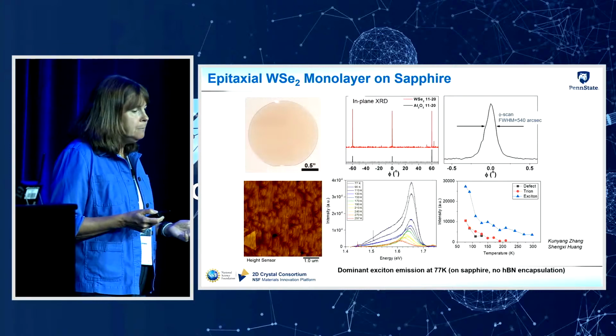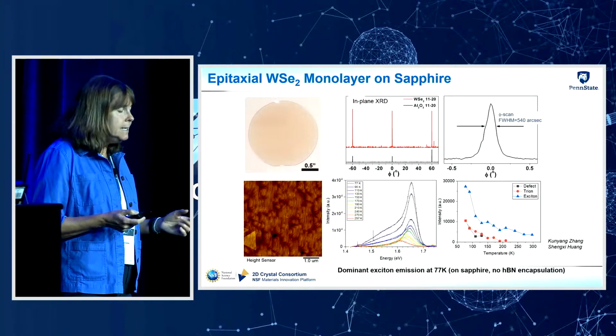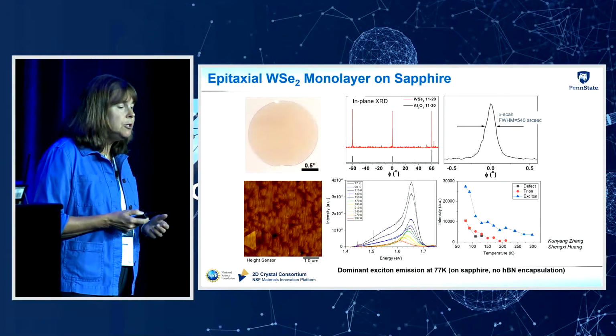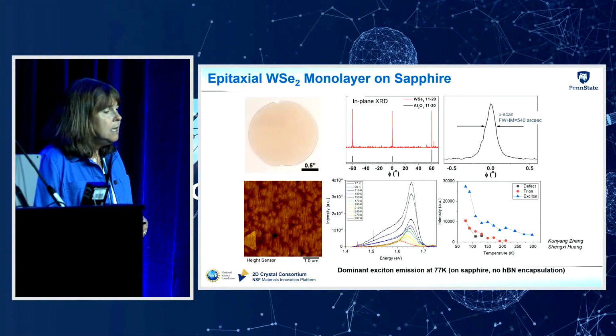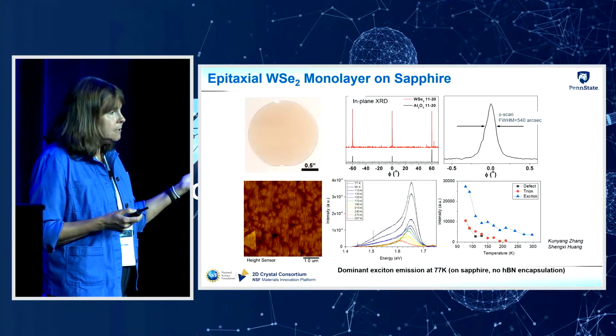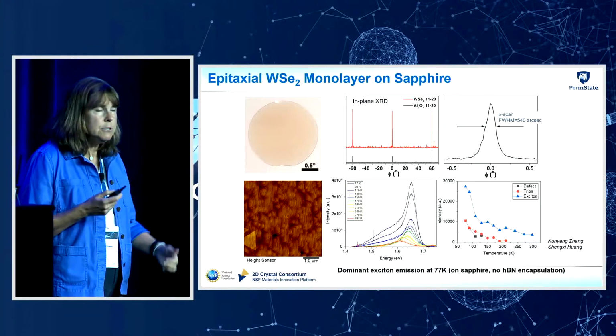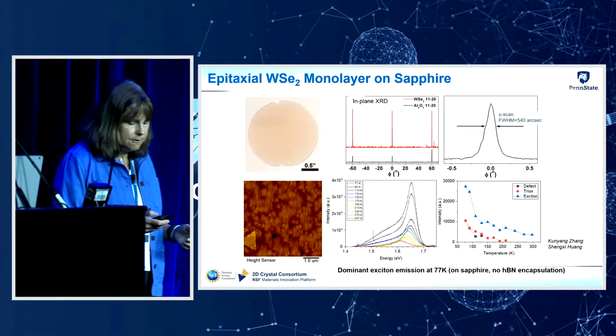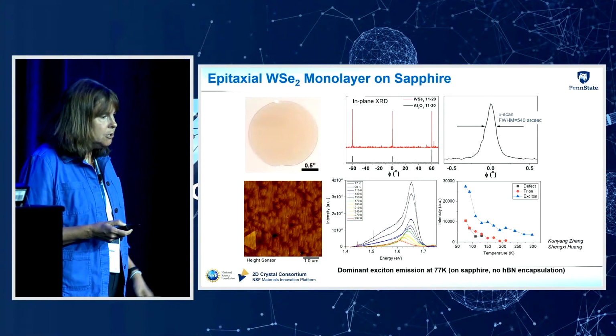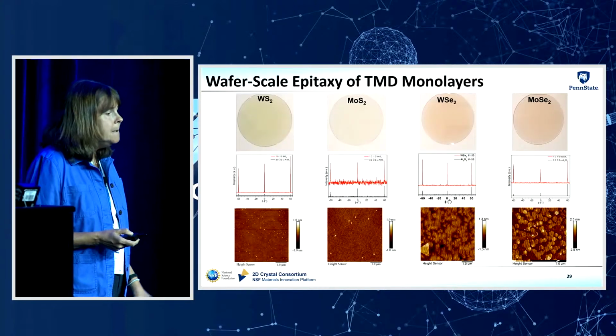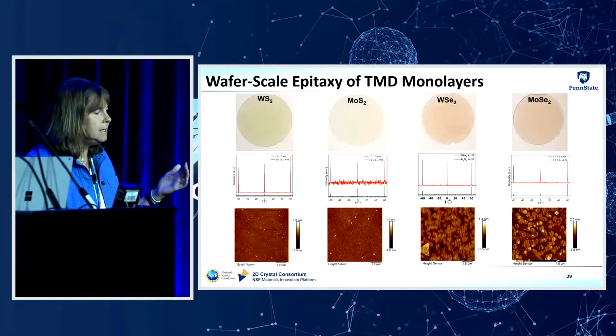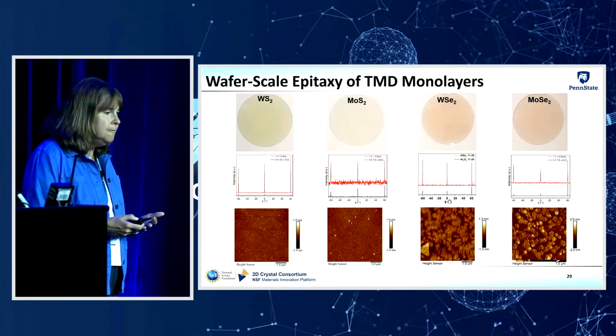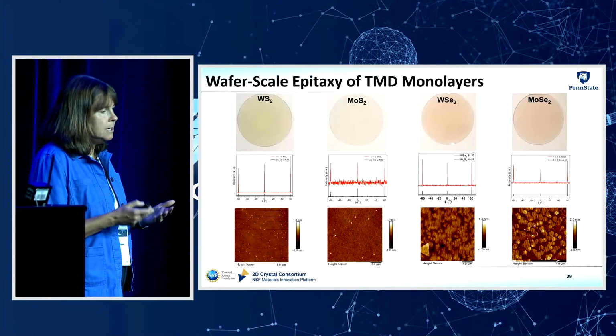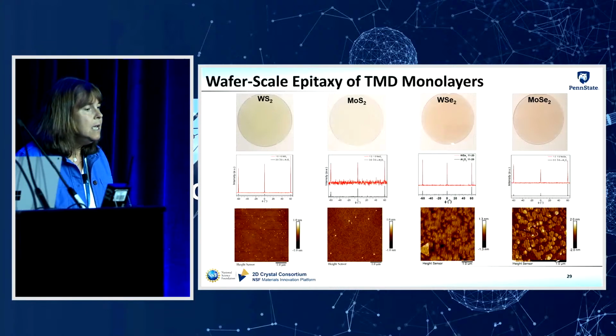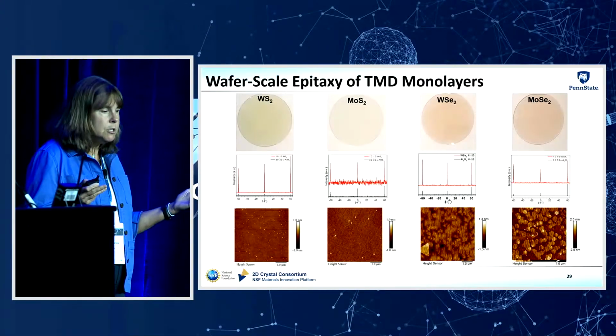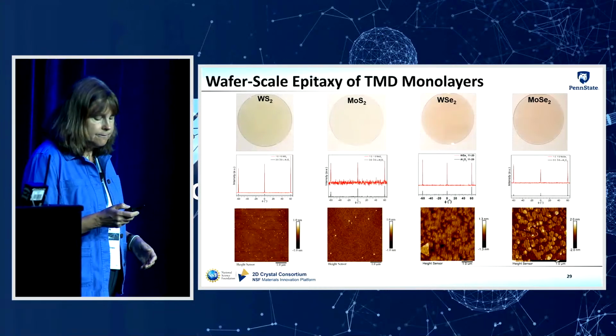Also, if we do variable temperature photoluminescence measurements, we see luminescence at low temperature that's dominated by excitons. And we have a very low defect-related or defect-bound exciton emission, indicating that the level of defects in our films is not too high. So they look good overall in terms of the properties. And then in addition to the tungsten diselenide that I talked about, we can also grow sulfides using this process, so tungsten disulfide and moly disulfide, as well as moly diselenide. And the films all grow epitaxially on the sapphire surface.